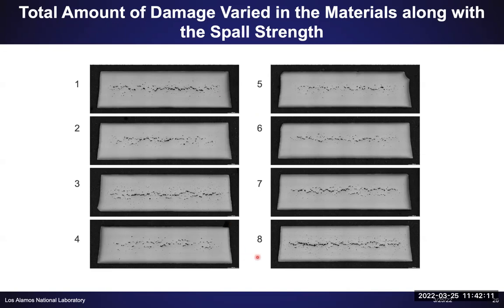So here are micrographs for some of the samples that were subjected to shock loading. The center black region shows the damage or the void that formed in the sample. And one thing to notice is some of the samples like sample 3 and sample 8, in addition to the Spall plane, have a lot of porosity in the bulk of the samples. So these passed our initial density and hardness screening, but obviously these were not the best built samples.